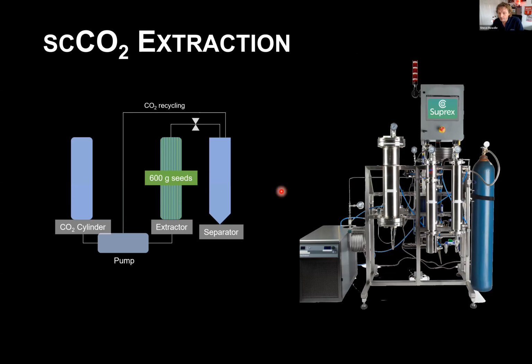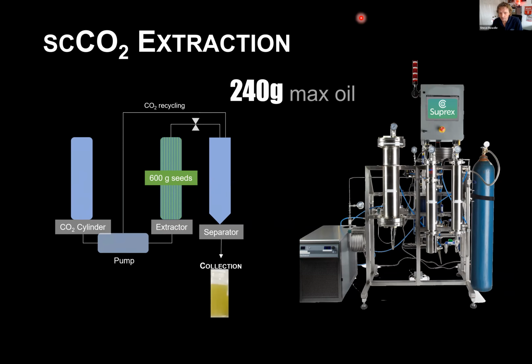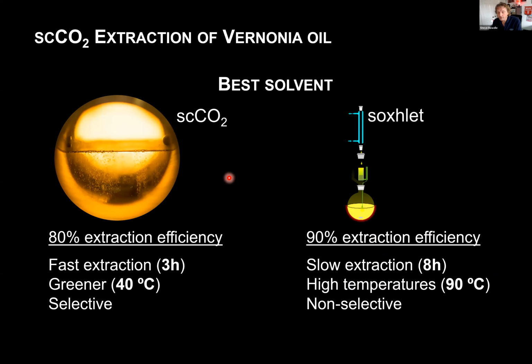The way that we extracted the oil was actually using supercritical fluids. Just in the same way that you can extract caffeine from coffee beans, we extracted the Vernonia oil from the Vernonia seeds. We took it to a commercial operation in the UK, and we had 600 grams of seeds. We put it into the apparatus and pumped CO2 through, and it very effectively produced 240 grams of oil. We could then take this oil, and it was very pure and very clean, and we could start to work with it.